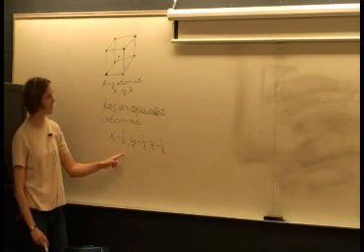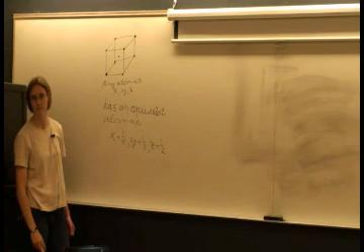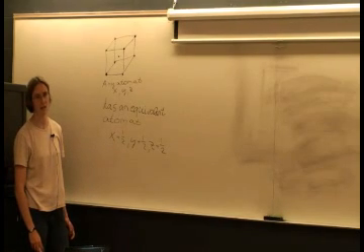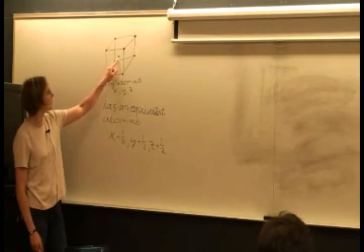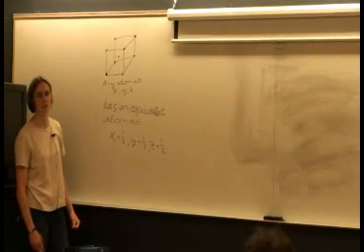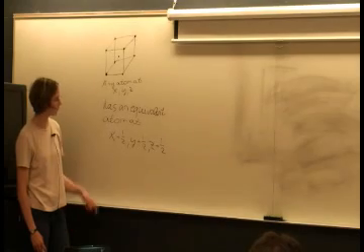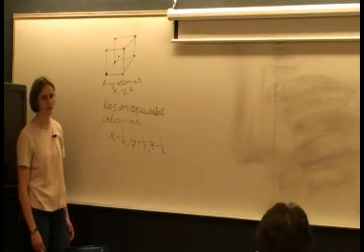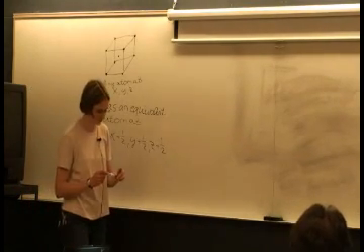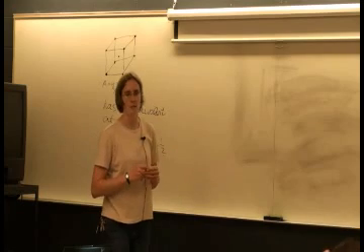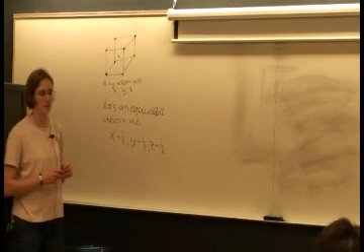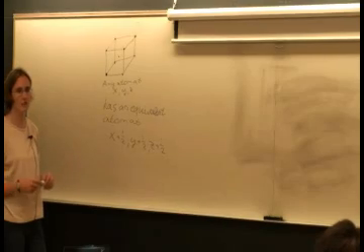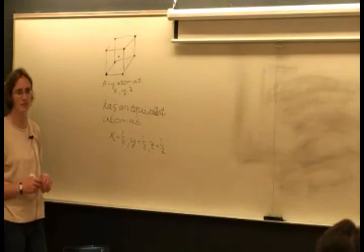So this is what body centering means. Any atom at XYZ has an equivalent atom that is related to it by the body centering translation. So that's X plus 1/2, Y plus 1/2, Z plus 1/2. Right? Now, in order to look at whether or not we see intensity somewhere, we need to look at those structure factors that we introduced today, right?